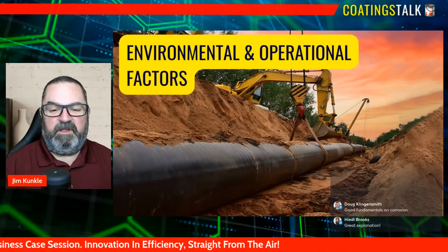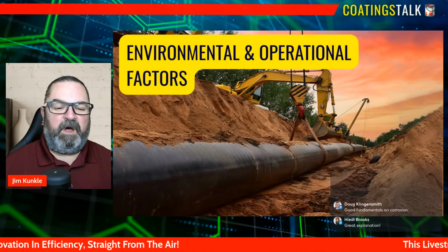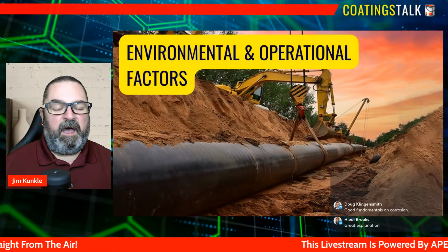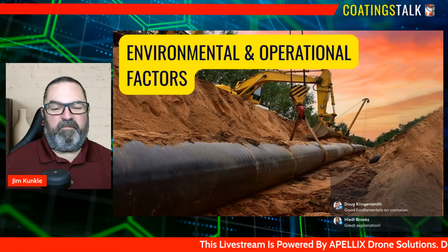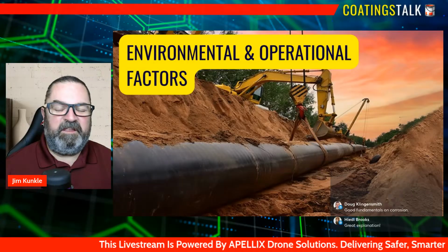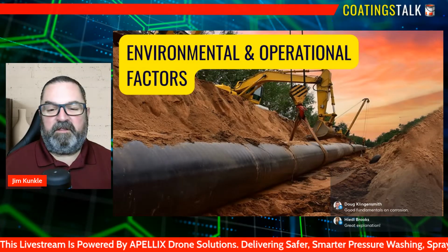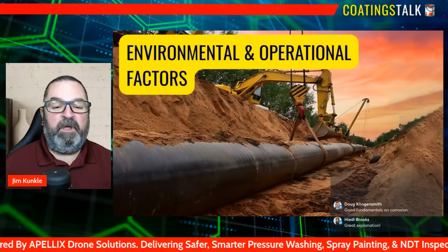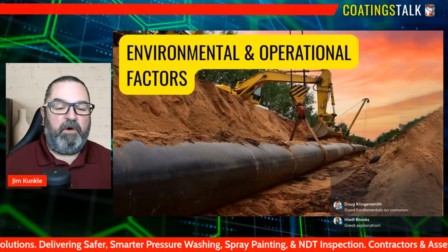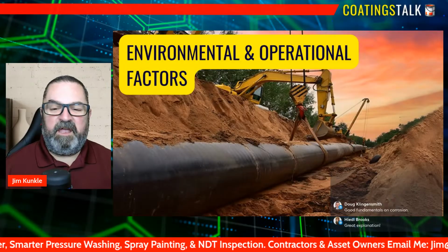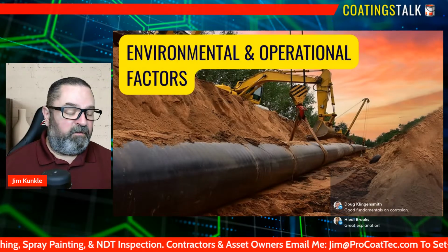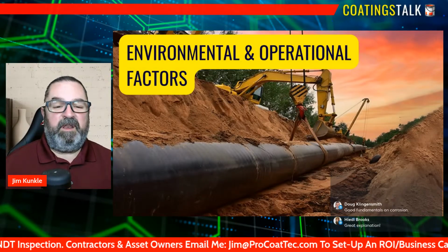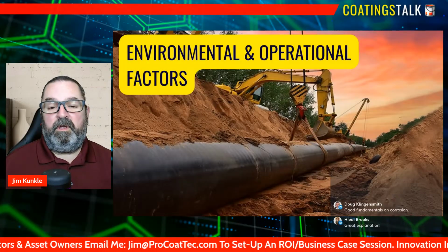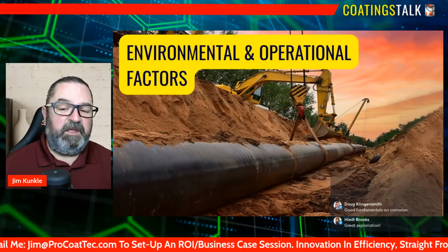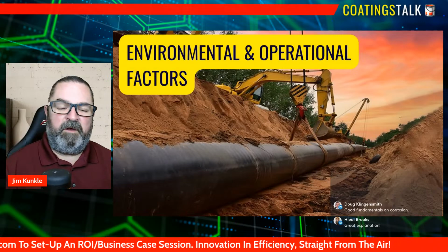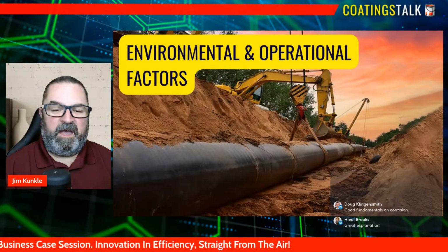Even the most advanced coating system will fail prematurely if it's applied over inadequate surface preparation, contaminated steel, or inconsistent film thickness. Thin spots, overspray, missed edges, and improper curing conditions all create weak points where corrosion can initiate. In many cases, the coating may look acceptable on the first day, but hidden defects like embedded dust, trapped solvents, or incomplete surface cleaning undermine the adhesion from the moment the asset enters service.